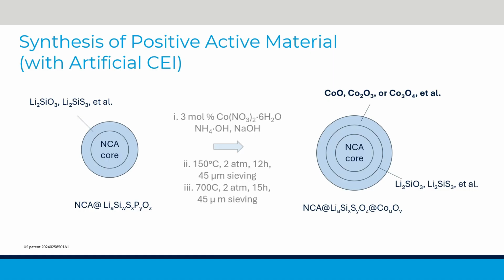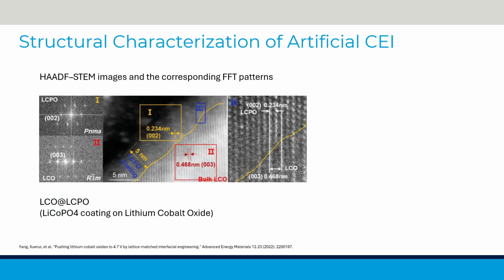In an example, one more step is taken to coat cobalt on the outermost layer. Cobalt hydroxide is converted into cobalt oxides on the particle surface and provides additional stability. Besides cobalt, zirconium or a combined coating is also explored. There are several ways to obtain structural information about an artificial CEI.